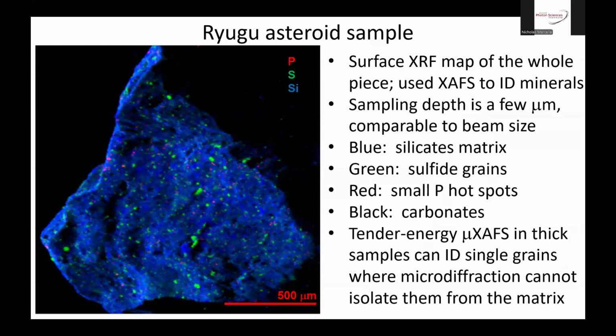So coming back to the Ryugu sample, this is a surface map of the whole grain. We didn't want to cut these grains because we had to send them back. So for the tender energies, again, this goes back to the sampling depth. Sampling depth is only a few microns, so we could look at the surface of the whole grain and not worry about it. At this energy range, even a thin section of a rock material is infinitely thick to the beam. So that kind of makes it easier in some cases.